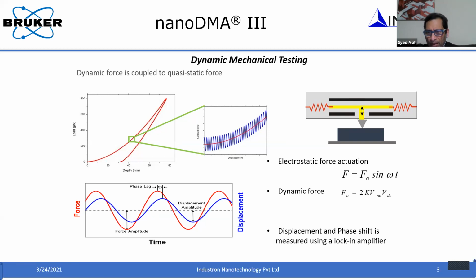So for that, we use a lock-in amplifier. It is basically nothing but a vector amplifier where you can listen to that particular frequency and measure the response. In a very simple way, you apply an oscillatory force, that is F sin omega t, and then you measure the displacement response, and from the relationship between the applied oscillation and the measured displacement response, you can infer many things. For example, when you do it on an elastic material, the force and the displacement will be in phase. There won't be any phase shift between the force and the displacement. That is typical for an elastic material. But if you do it on a viscoelastic material, because of its nature, there is damping. It will delay the response so that you have a phase shift between the force that you applied and the displacement that you measure.